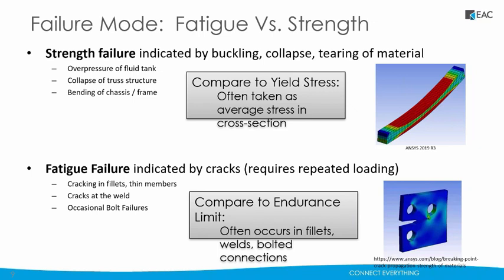If you tighten down a nut, you get some yielding at the interface, local yielding. And so the yielding is the issue. Really, what we're worried about is large scale yielding. And so the problem is never as simple, and that's even on the strength side. But then what we find is that many of our products actually don't fail in strength. In fact, I'd say the majority of them actually fail in a fatigue type situation.